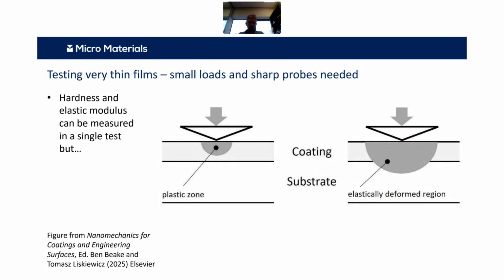So if we wanted the hardness of a thin film on a less hard substrate, essentially, you need to do a sufficiently small indentation so that the plastic stress field remains within the coating. And if you do enough of those, you get reliable values for the hardness of the coating, provided you've got full plasticity. On the right is the associated elastic field shown schematically for the same sized indent. And you can see it's a much bigger field, so it's a much more far field effect. And what that's telling you essentially is that your elastic information is coming from further into the structure. So ISO 14577 gives you a way around that, where you can do measurements at different depths and extrapolate to zero depth to get this coating-only value of stiffness.